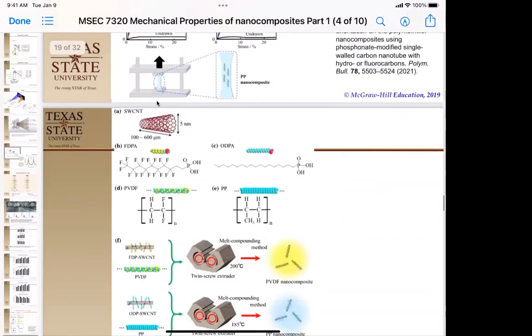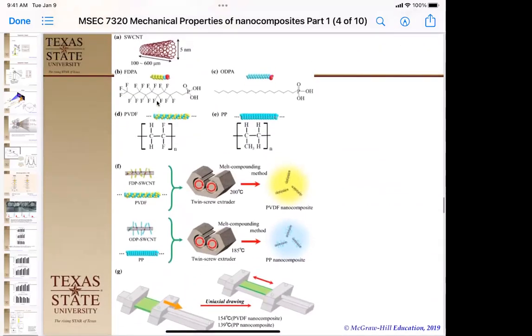So this is kind of a little bit more of how they do it. They take the carbon nanotube and modify it with these phosphonate salts. One of the phosphonate salts has fluorine on it to make it more compatible with the polyvinylidene fluoride. So, a fluorinated polymer and a fluorinated functionalizing group on the carbon nanotube. Now on the polypropylene, they use a standard polyolefin chain, like a dodecyl chain or whatever, and that's going to make it compatible with polypropylene.